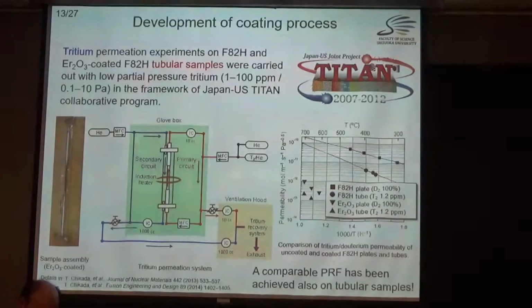In the collaboration framework of the Japan-US joint project, TITAN, we used tritium with a tubular sample. This is a tube, and an erbium oxide coated sample was buried with the other components. Then tritium goes through the inside of the tubular sample, and the permeated tritium was collected by purge gas, purge helium, to go to an ionizing chamber to collect the tritium.